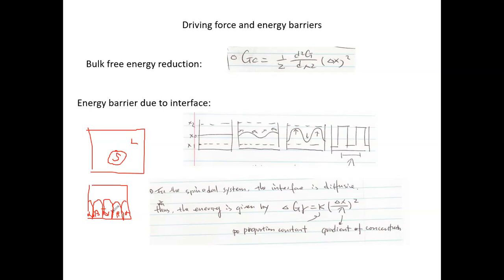So now the question for us for the spinodal decomposition is, do you have an interface in this case? And if so, how do we take into account this increase of energy or energy barrier due to the interface? Okay, so that's the question, which is kind of interesting, and it's quite different from all we know. So the first question: is there an interface in the system?